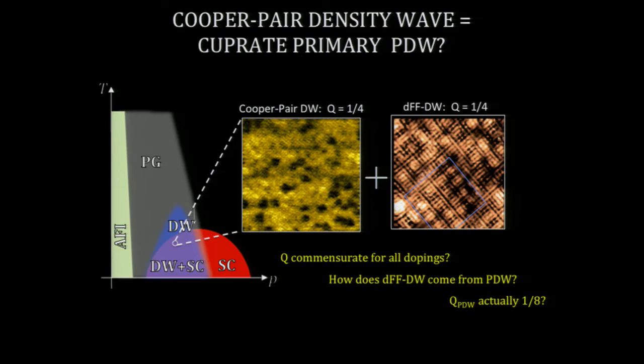That leads us to ask, well, is it possible that the charge order is modulating the superfluid? Or is it that you have a pair density wave, which then gives rise to a charge density wave in the system? And that's something that we actually still have to find out. And that's going to require some more doping-dependent studies. It's going to require some more theoretical work. And one of the smoking gun pieces of evidence which we hope to find: I showed you a 4-unit cell modulated Cooper pair density wave. Is it possible that it's not really 4-unit cell, but 8-unit cell? So think about that for a moment.